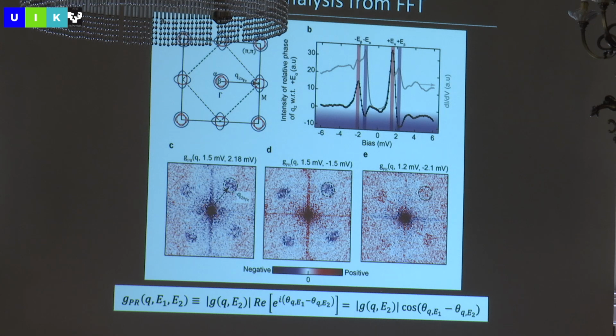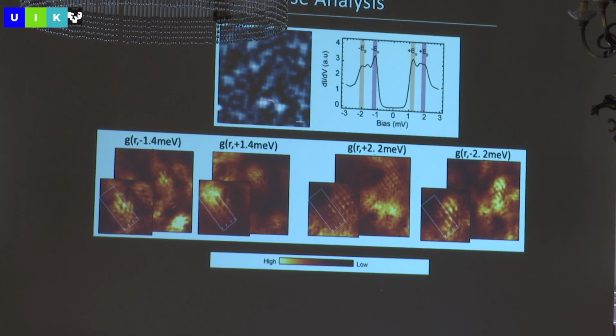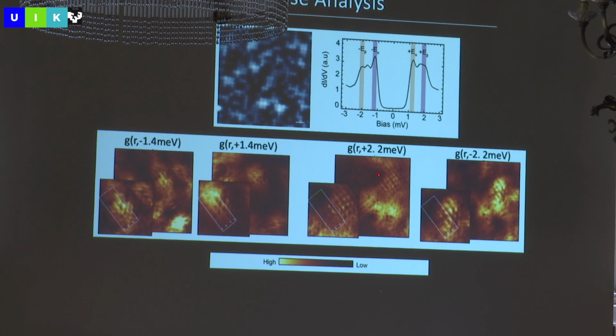Okay. But you can see this in real space. It's actually really funny that you mentioned real space. You can actually see it in real space. It's so hard to see here, but you can see all these waves. The pattern of these waves shifts in real space actually. So there's a real shift pattern: you have waves, and if you look at one energy and another energy, the pattern is shifted by half. Okay. That's the pi phase shift.